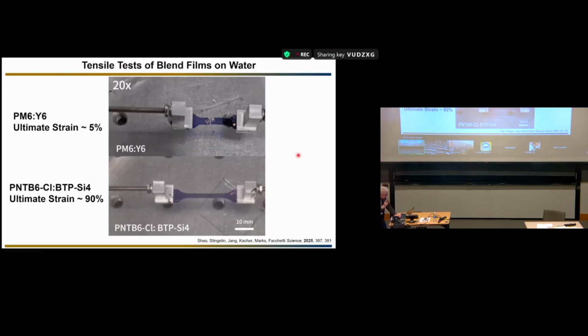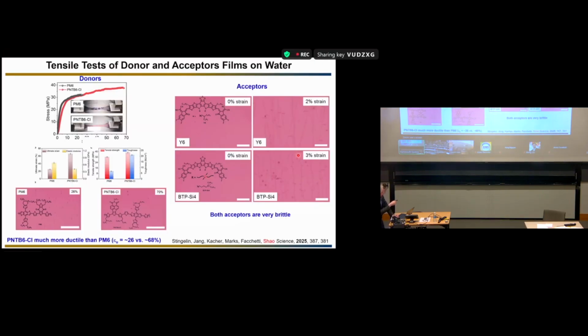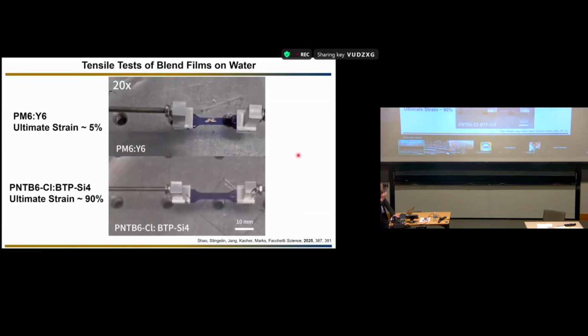So you see there is a very big difference. When you add this one, you are not embrittling the polymer. You actually enhance the elasticity. So this new acceptor acts as an anti-plasticizer, instead of this acceptor acting as a plasticizer. So fundamentally it is different. This is due to different things that we studied that I don't have time to discuss, but basically you have to believe me, this is mostly due to the miscibility, and the fact that this enhanced miscibility in the donor phase reduces the energy for the beta relaxation of the polymer backbone, something that other acceptors cannot do.